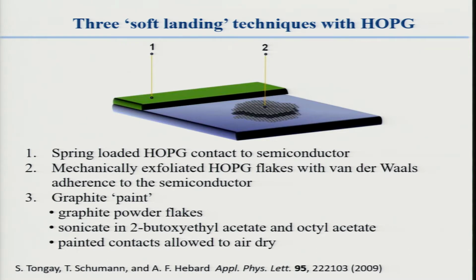So we did a number of crude experiments, first just spring loading. The HOPG stands for highly oriented pyrolytic graphite. Just pressed it down. Sometimes we just got light flakes, and Van der Waals adhesion, where they just sucked down onto the substrate. And we even made a paint, which we could paint our barriers by making flakes, and they would line up and make a Schottky contact.